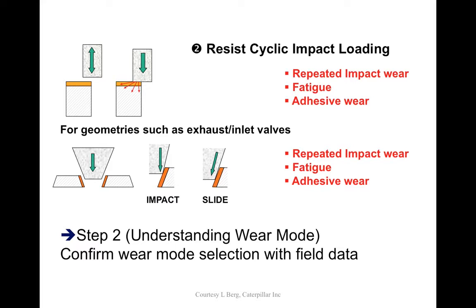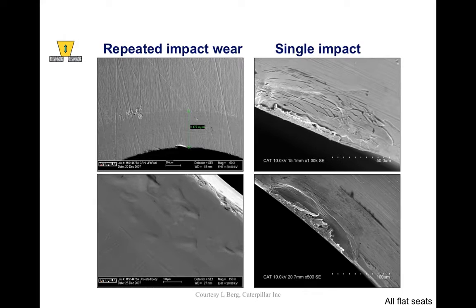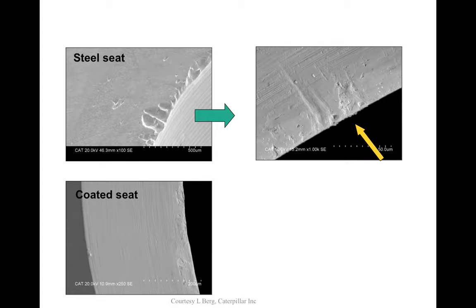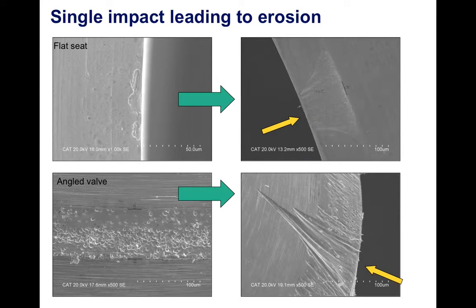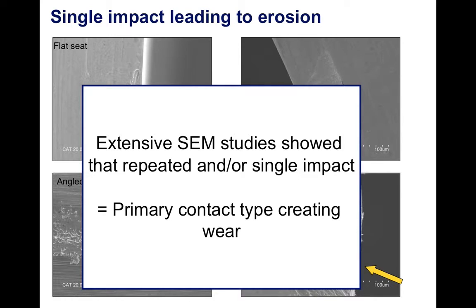So you understand the wear mode, then you've got to confirm the wear mode with field trials. So what they then do is they do the tests, and they make sure that the behavior they see from the coating is simulated in the actual field trial and the in laboratory test. So they'll do lots of microscopy just to check if the failure of the coating is as they see in the field. So an awful lot of that kind of microscopy to understand how it operates and what kind of deformation and bedding in they get. And they also then confirm what are the primary contact and wear types. So in this case, they really did identify that impact wear was important in their application. So they did a lot of impact testing, and they got the solution that they were going for.